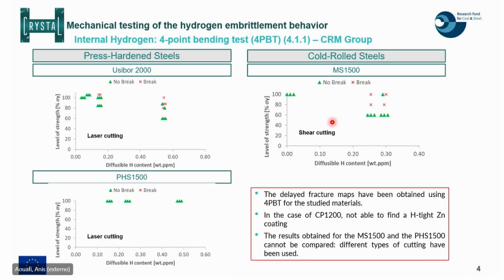And with this graph, we highlight the delayed fracture map that we could obtain using this test in this condition. On the left, it's highlighted the obtained delayed fracture map for MS 1500, and in this case, the edge was sheared. So we could not compare the behavior of MS 1500 regarding PHS 1500 because a different type of cutting has been used for both materials. Another remark, as mentioned by Mélodie before, we were not able to have an H-tight zinc coating on the CP1200. We are still working on it. We are surprised by that, and we were not able to have an equivalent delayed fracture map compared to the other materials.